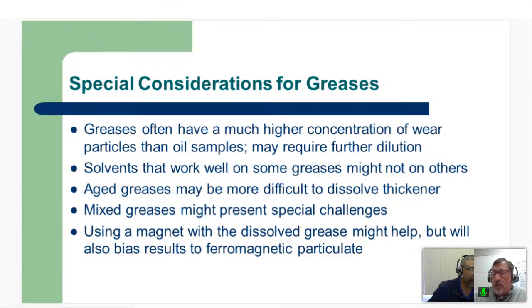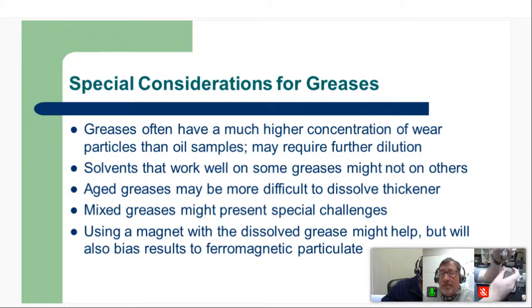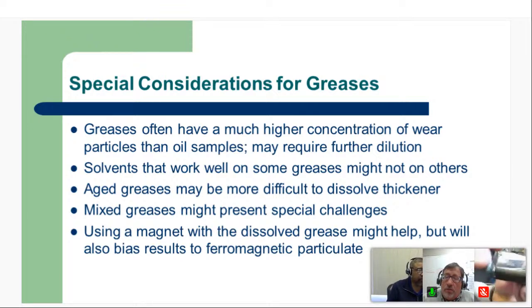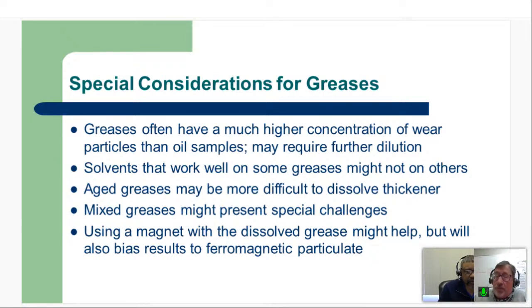Richard, do you have the chance to kind of show what our setup might look like? It's not too elaborate of a setup. We're basically taking the dissolved grease. So we've got the solvent in there. Our substrates will still be in there. Can you flip that over again, Richard, just to show that quick? And when you do that, you can see this. Just hold it up a little bit further. You can see the plastic substrates still in there, right? And so most of the grease has been taken off of there, but now you've got the solvent, the thickener, and the particles that are of interest. And so you can then use a high magnetic strength magnet to kind of hold the particles to the bottom of that, and then allow the solvent and the thickener, and some of the non-ferrous particles too, to be washed away. Yeah.